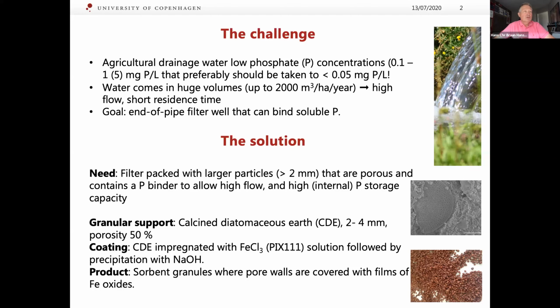Could we also have internal storage in the filter granules? So we looked at porous granular supports, and here took a calcined diatomaceous earth. It can be provided in particles of 2 to 4 millimeters, and the internal porosity is also very high. Therefore, our strategy has been to impregnate and precipitate the iron oxide in the internal space of these diatomaceous earth granules. You can see here to the right that we have the diatomite shells, and it's full of pores, and then we precipitate the iron oxide in it, and the material looks like an iron oxide coated sand, you can see.